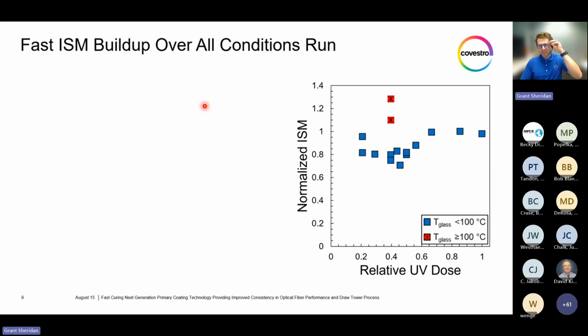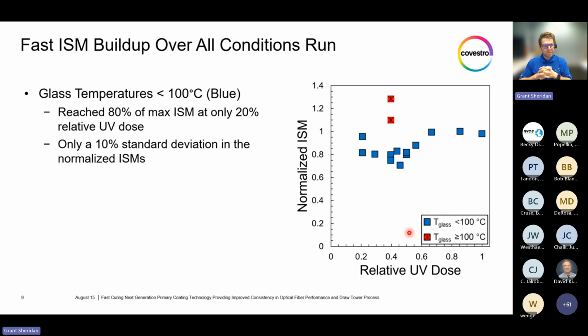Now, we looked at RAU, so we have to look at the in situ modulus and normalized in situ modulus buildup versus the relative UV dose, shown here again for glass temperatures below 100 degrees C and those above 100 degrees C. If we look at the blue data, the glass temperatures below 100 degrees C, we can see that we reached about 80% of the in situ modulus at only 20% UV dose again. So once again, very fast curing, very fast modulus buildup to protect the glass and develop the mechanical properties.